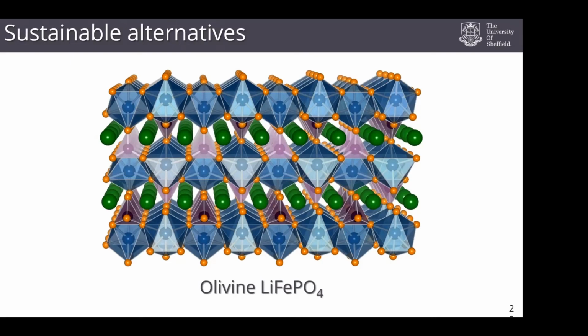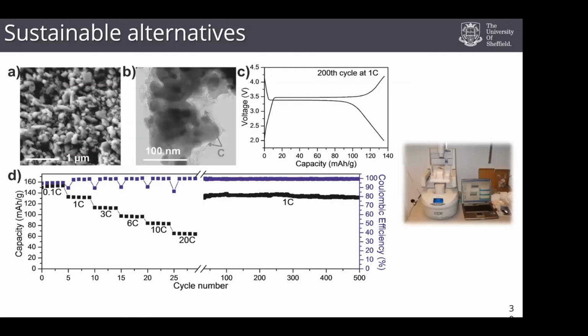The only problem is sometimes when you have one-dimensional diffusion like this, if an iron was to sit where a lithium is, this would be called an anti-site defect. And that channel is now blocked and can't be used anymore. And that limits your capacity. So we need to try to find ways to make materials that resemble this kind of structure, with fewer defects in them. And that's what we've been doing.